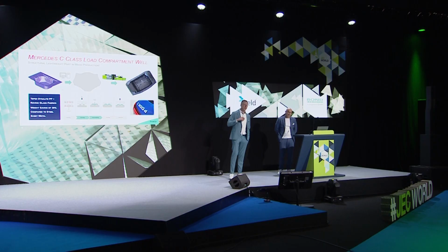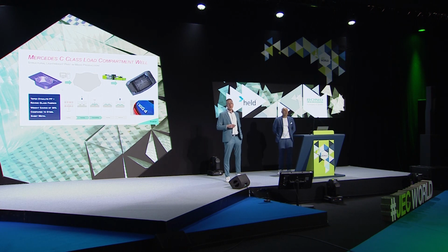And the idea behind this is to replace a steel well, which would be around 30% heavier in weight. And this is a semi-structural part. In the case of a crash, it would have to contain all these liquids that could be coming out of the battery. On the other side, it must prevent media from coming into this well, and so on. And as I mentioned, compared to a steel well, we achieved here a weight saving of around 30% with more or less the same boundary conditions, like same system pricing and shorter cycle times.